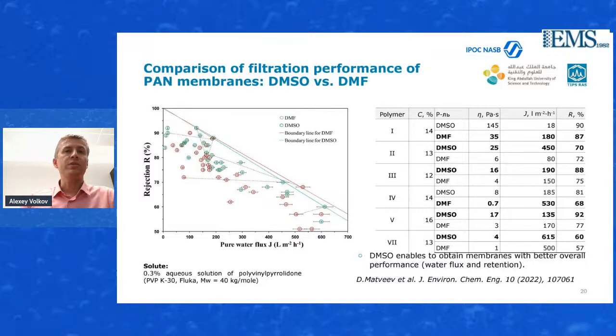And if we make a comparison of the DMSO and also DMF, we linked 2 points. If the point, let's say for the DMSO green point, is on the upper bound, the dashed line goes to the same composition that was used for casting the membrane, but from another solvent. And what we can see here is that a replacement of DMF by DMSO usually allows us getting a higher flux and a higher rejection. So once again, if we take into account all of the things, we can play around with not only the polymer, but also the solvent nature to optimize and to improve the separation performance of the membranes.